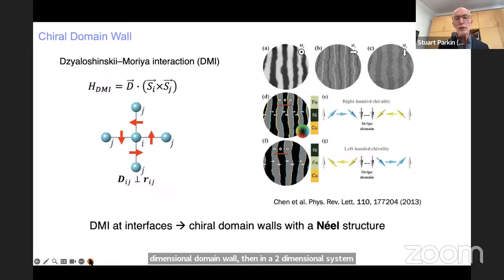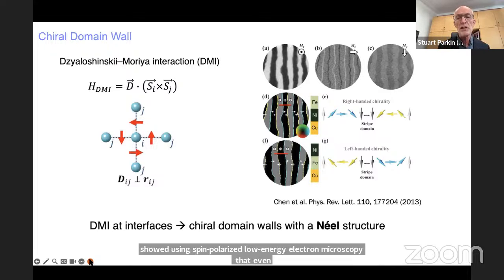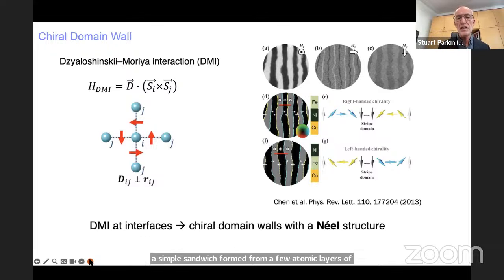So first, let me talk about domain walls. In a one-dimensional system with one-dimensional domain walls, the domain walls themselves, in which the magnetization rotates from up to down, can rotate from up to down in a chiral fashion. And shown here is some very nice work from more than 10 years ago from Fudan University, where this group showed, using spin-polarized low-energy electron microscopy, that even a simple sandwich formed from a few atomic layers of iron and nickel, when placed on copper, you form domain walls which have a chiral structure.